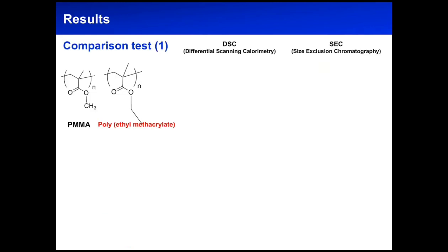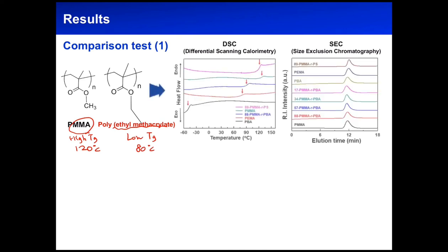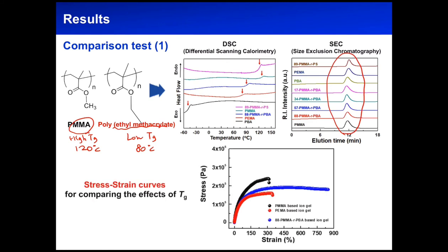To figure out the origin of stretchability, we synthesized PMMA and PEA homopolymer, which have high and low glass transition temperature. For example, PMMA homopolymer has 120 Celsius degrees, and PEA homopolymer has 80 Celsius degrees for Tg. Some researchers argue that the low Tg is a crucial factor for chain flexibility. Therefore, we adjusted the other factors at the same condition, such as similar molecular size or same concentration of ionic liquid, for just comparing the Tg effect.